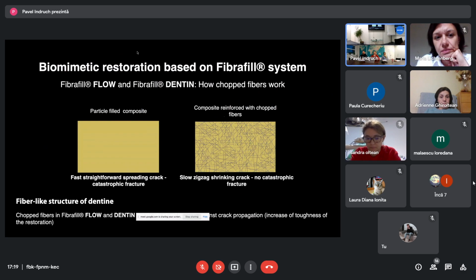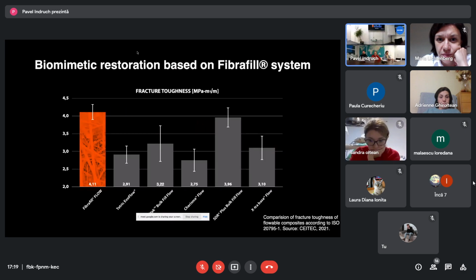You can see that the crack spreads fast and straightforward in homogeneous materials like conventional composites, which consist only of organic matrix and reinforcing fillers. But if you put a structural barrier to stop the crack propagation, the energy of fracture needed to be absorbed by the fibers is much higher, and there is no catastrophic failure of fracture in this case. This is maybe easily understandable.